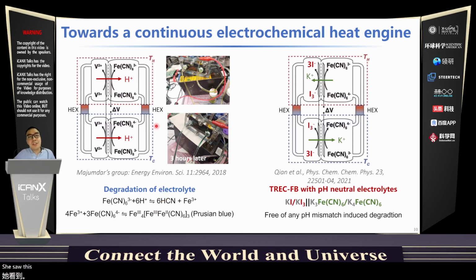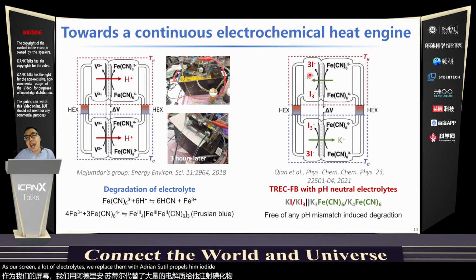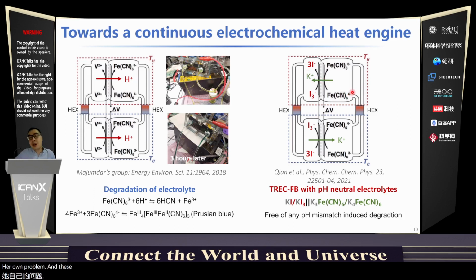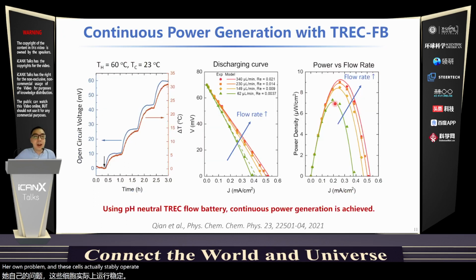To solve this problem, we screened a lot of electrolytes, and we replace the vanadium with potassium iodide and triiodide. Instead of proton exchange, we do potassium ion exchange. And in doing so, both electrolytes are pH neutral. We don't have to worry about acid-induced corrosion problems. And this cell can stably operate without degradation. So as you can see, we do discharge tests. When the temperature rises, we can generate the voltage. We can also achieve steady state power.